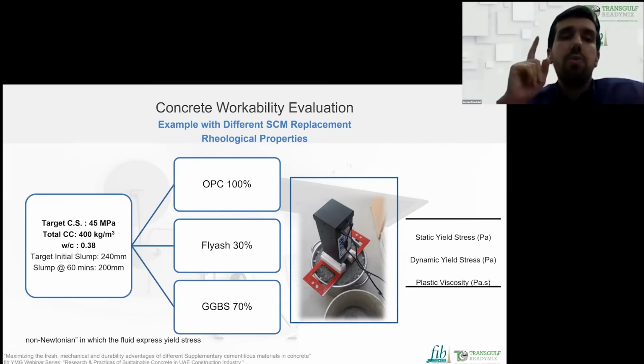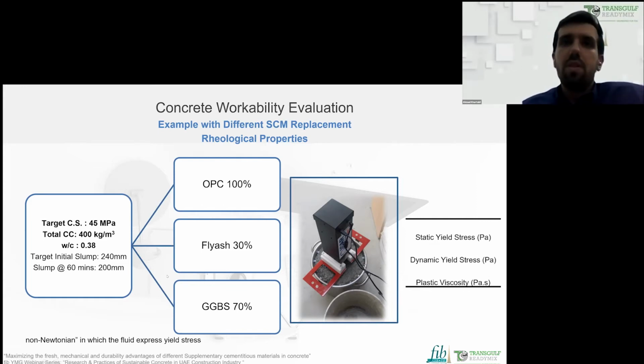So here, one concrete mix has a total cementitious content of 400 and a water cement ratio of 0.38. All the mixes have the same total cementitious content and the same water cement ratio, and of course the target strength here is 45 megapascal. The rheology was evaluated 1 hour after mixing, from adding the water, or from batching, at a slump of around 200 millimeters.